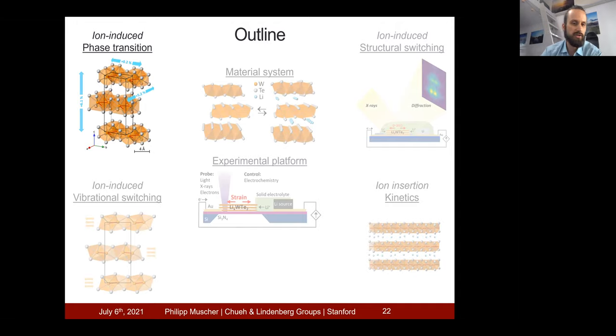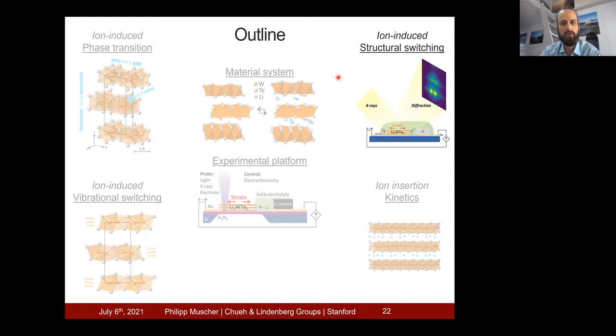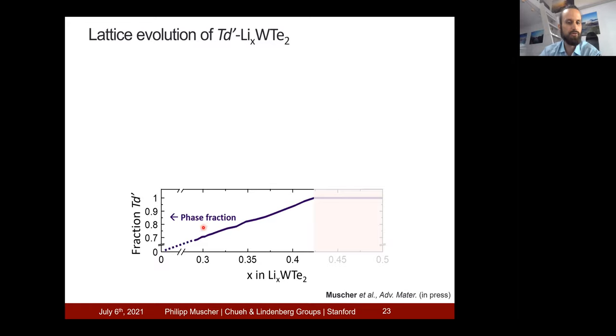So now I've shown you how the material transitions to the new phase. Now I want to come to how we can tune the structure of that new TD prime phase. For this, I'm using the data of multiple diffraction peaks. I can look at multiple diffraction peaks for the initial structure and multiple diffraction peaks of the new structure, and I can look at their relative intensities. And this informs the ratio of the two phases in the volume of the sample.